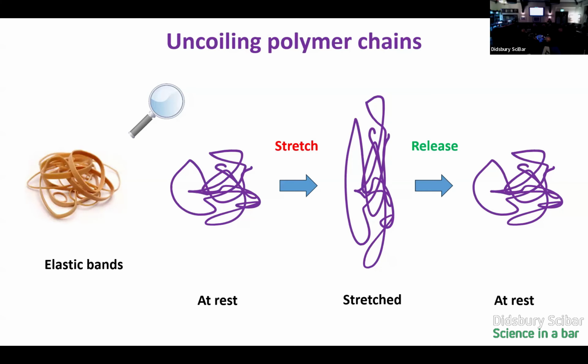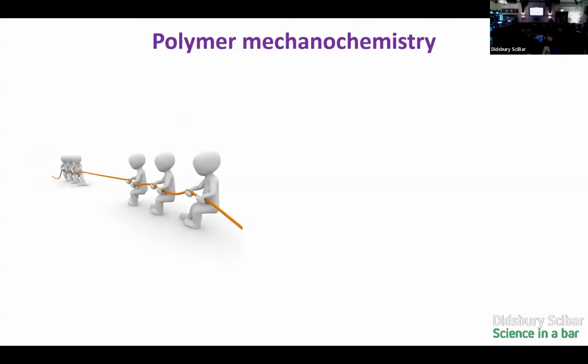Where the exciting things happen is what happens if we really, really stretch this? What happens if we really pull on the polymer chain? What can we get it to do? And that's where this field of polymer mechanochemistry comes in. What happens if we really, really, really stretch out these polymer chains? And the answer is if we pull them far enough and fast enough, essentially we can cause breaking of the chemical bonds in the polymer.